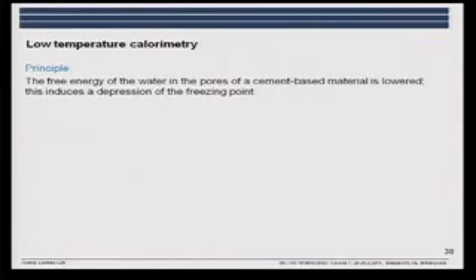The principle is that the free energy of the water in the pores is lowered due to the size of the pores, and that induces a freezing point depression. We also have a freezing point depression due to ions in the pore solution, but it's less than what we see due to the pores.